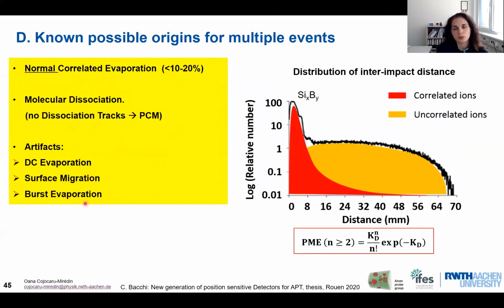So the question was also whether these multiple events are correlated in time and space. There is a very nice work done by Christian Baki at Rouen University, where they calculated and simulated the distribution of inter-impact distance of the multiple events. They found that the distribution of the inter-impact distances has two main contributions, so it's an overlap of two main contributions. One is related to the ions coming from the same emission site. These are our correlated ions in red. The other is ions related to the stochastic evaporation, and these are completely uncorrelated ions.